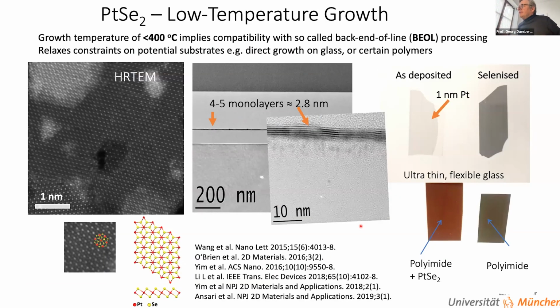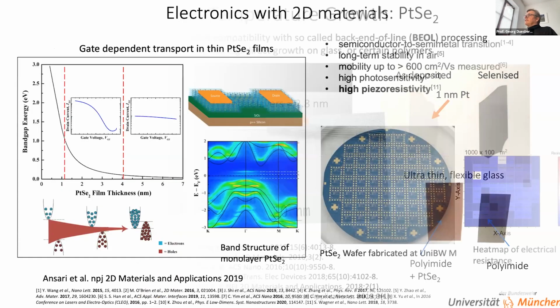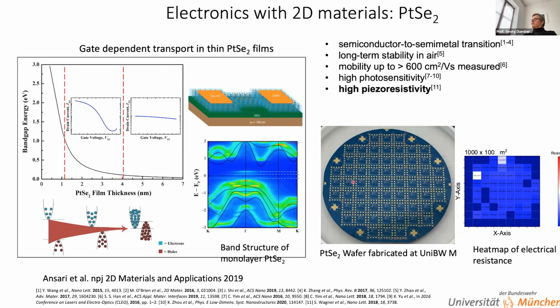If you look at it, it's crystalline in the nanometer range rather than the micrometer range. From the cross-sectional images, it nicely aligns. Platinum diselenide in this case has a 1T structure. And we can make nice layers, and as I said, the low temperature allows us even to grow on glass or plastics, as shown here. So we can make nice and also big films of this, and we can make wafers of this, as shown here.